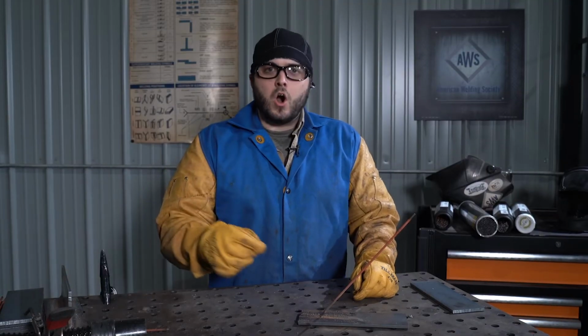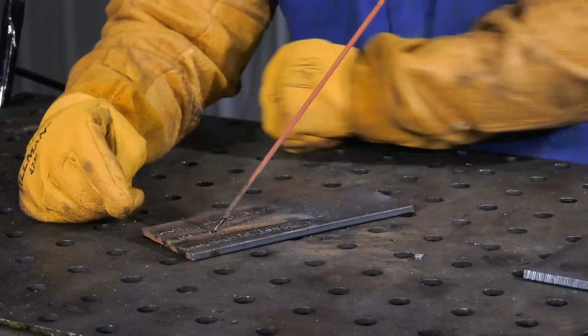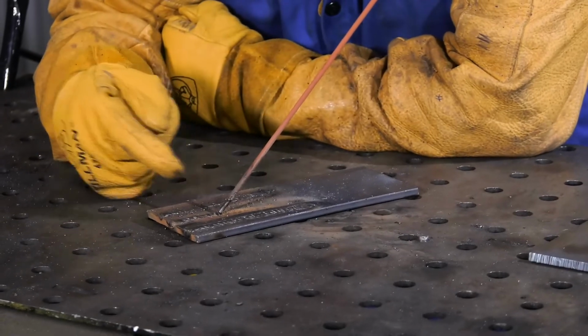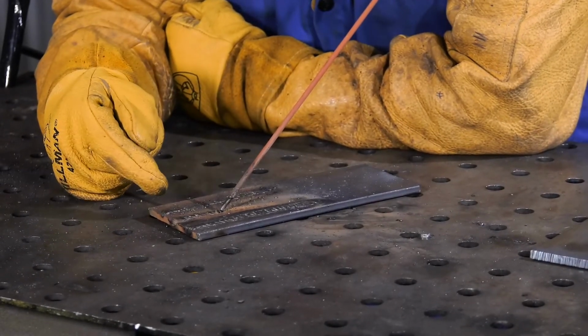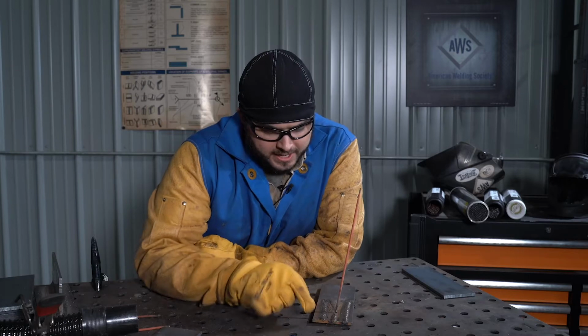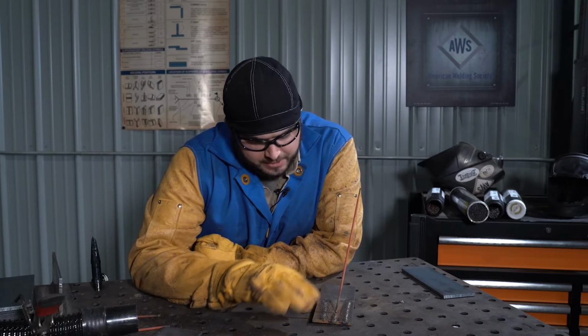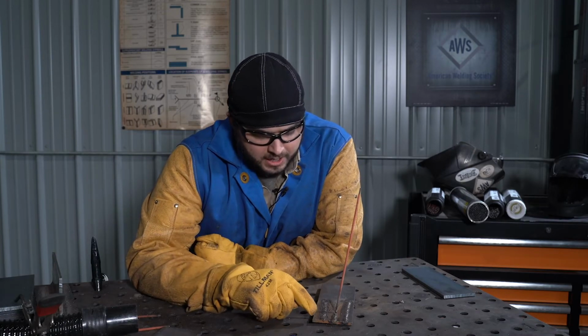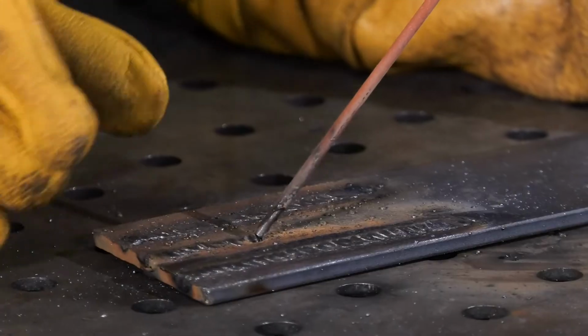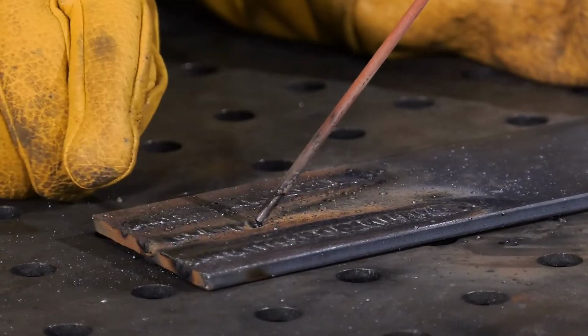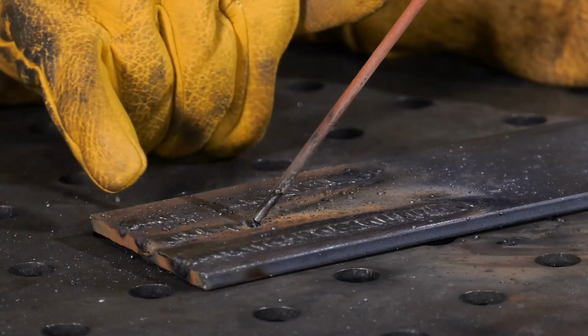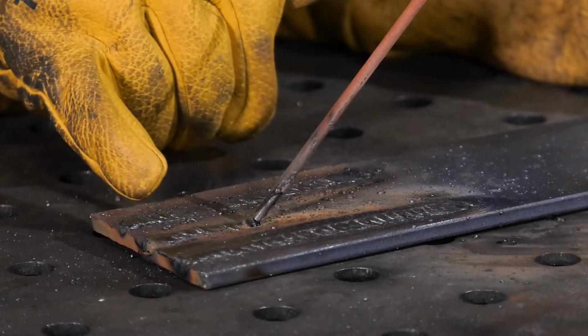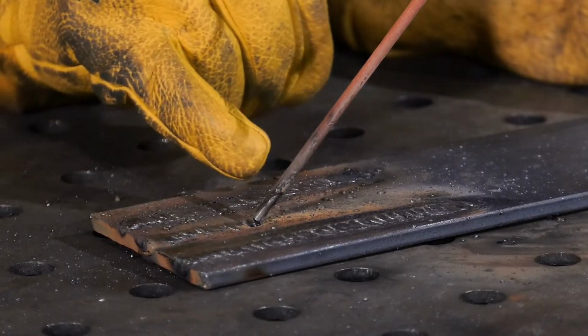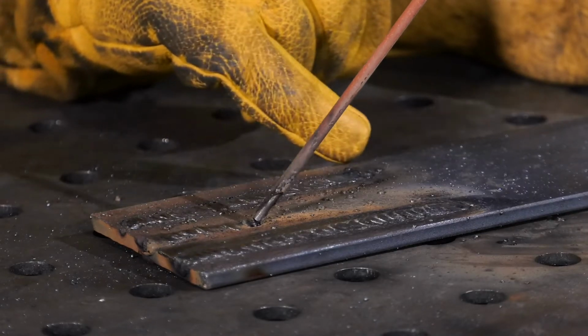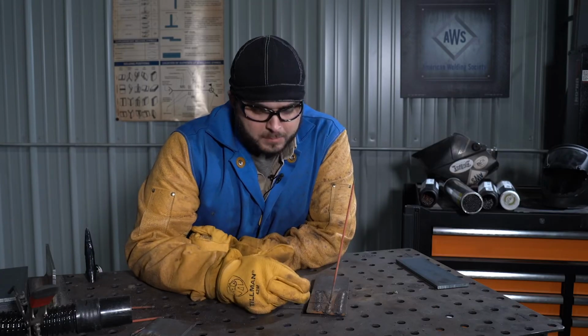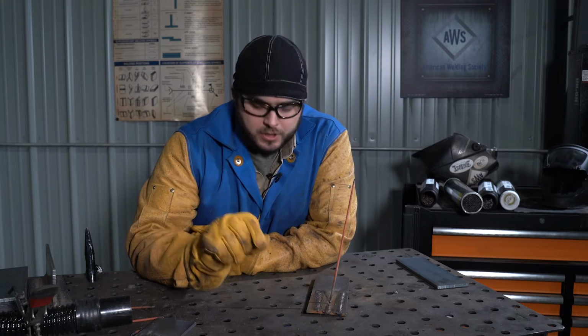Three, arc length. Too long. The distance from the end of that electrode to the surface of that material is too long, and what you'll observe is a flat weld profile, a lot of spatter, a very, very wide bead in most cases, and the profile along the toes of the weld will be very non-uniform. May even see some undercutting in some cases. To remedy that, simply bring that arc length down closer.